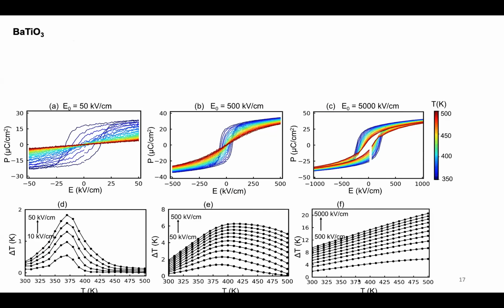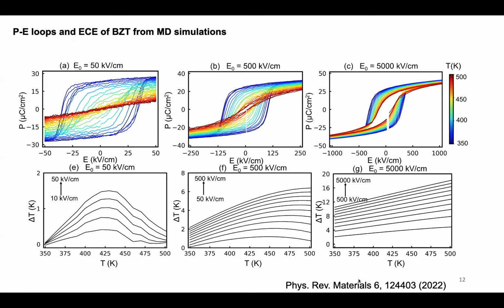Okay, but I'm trying to understand the point of view in your simulation. So you mean that in the simulation, if you don't do any poling, you have to move to the next stage maybe, and by poling you go towards a more homogeneous state. Yeah, the poling might create a monodomain state. So with the largest field, like in the theoretical simulations, you can see the field is 5000 kV/cm. So it's very huge. So that creates a monodomain state kind of stuff.